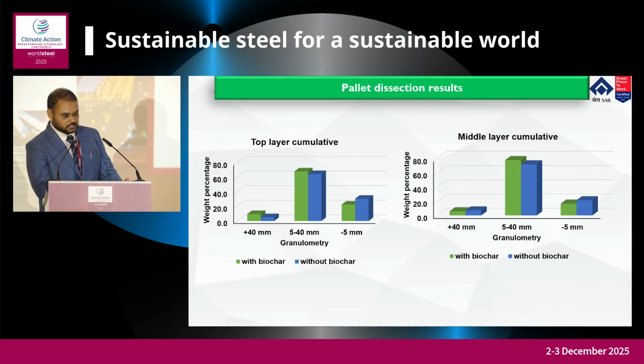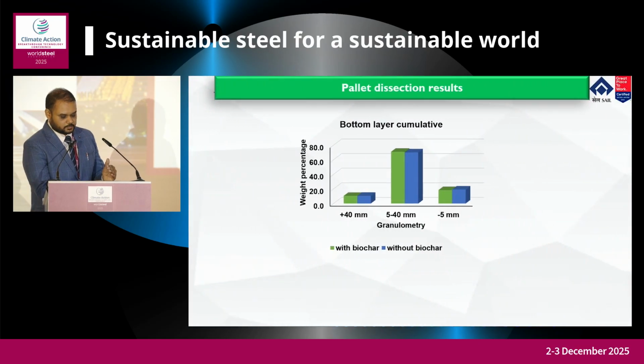So from the values, we can see that the top layer, which is weaker because of its thermal shock and heat insufficiency, has been partially solved with the biochar additions. And these figures have ultimately been effective in having good blast furnace grade sinter generation at Durgapur Steel Plant.